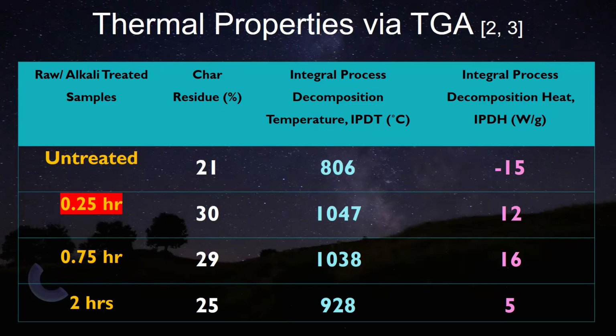So we can see that when it is untreated, the char residue was 21%. When we treated that one, it actually increased significantly. However, as I told you before, with the prolonged treatment, there is a distinct probability that cellulose would be damaged, and therefore the value for 2 hours is down, going to 25%. IPDT is an interesting property that was first introduced by Doyle in around 1961 or 65. That means this value actually encompasses the whole graphical scenario of this thermal properties. And because this biofiber is composed of hemicellulose, cellulose, and lignin, all three compositions have a distinct thermal characteristic.